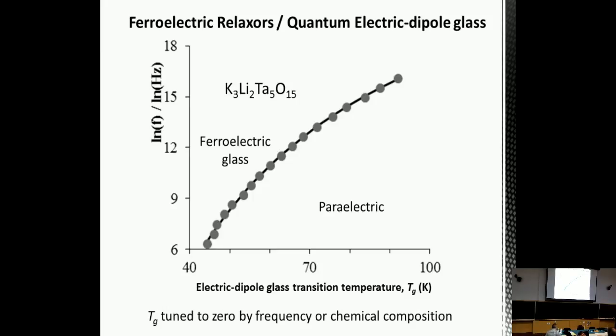This is new work which is just coming out soon. So at the moment, the role of disorder is not known in this case as yet, but it can be made. This particular work is on polycrystalline ceramics. Single crystals have not yet been prepared, but there are cases where you can then tune a dielectric electric dipole glass transition to absolute 0. We really don't know whether it's a self-generated one or whether it's due to oxygen vacancies or so in this case.